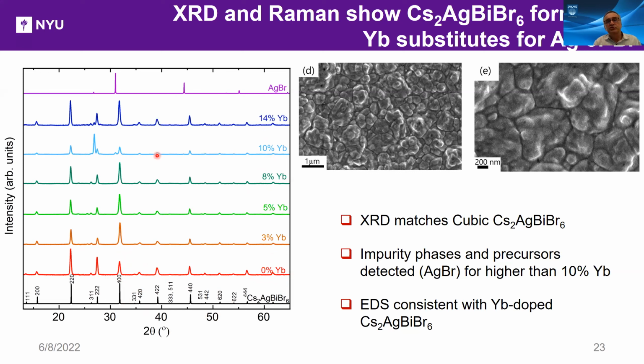We detect impurity phases when the ytterbium concentration is in excess of 10%. So here, for example, we have excess silver bromide. And we think that's because ytterbium substituting to silver might kick out some silver bromide. That's how we get the silver bromide. EDS is consistent with ytterbium doped 2116 stoichiometry.